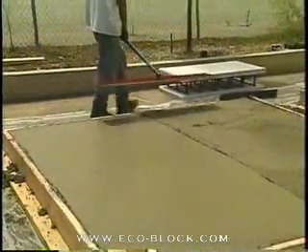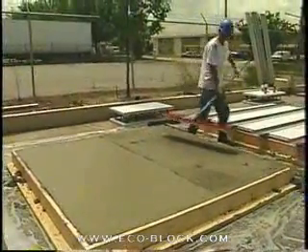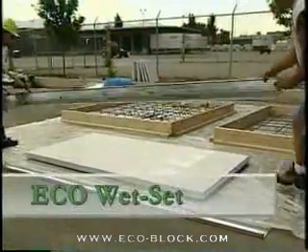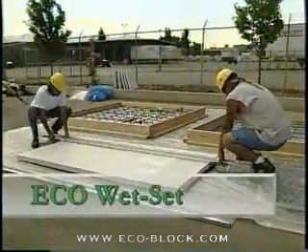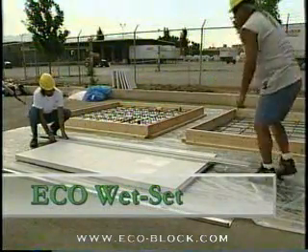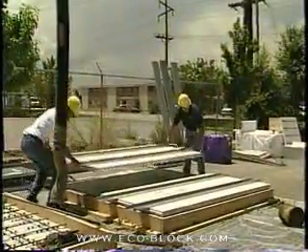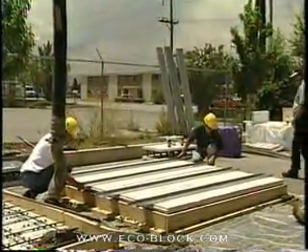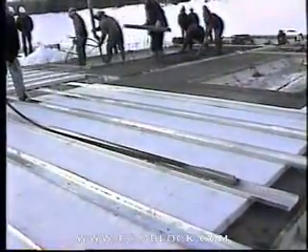There are three methods for using ECOBLOCK insulating panels in tilt-up construction: wet set, preset, and two-sided. ECO wet set involves setting assemblies of ECOBLOCK insulating panels — temporarily held together with strong backs — into freshly placed concrete. After the concrete has been vibrated and screeded, the panel arrays are set. A stinger vibrator will aid in consolidation around the webs. The panels may be walked on immediately after wet setting to remove the strong backs for reuse.